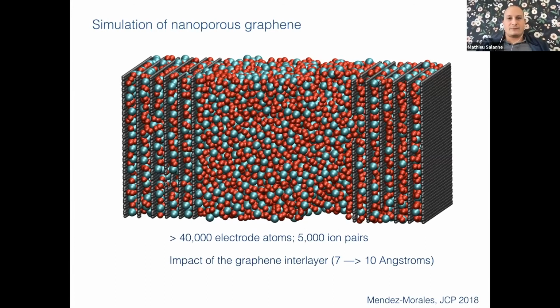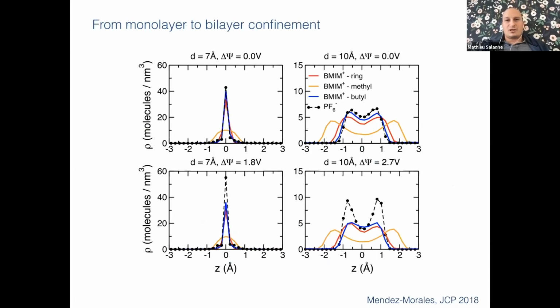So the idea is again to understand in particular the effect of the confinement. And so what we observe is that when you change from 7 angstrom to 10 angstrom, you have a very large structural difference, because in one case, you can only accommodate one layer of ions in the middle of the pore. While when you have 10 angstrom, you start to have more space, of course. So it's not really a bilayer, because in fact ions are in a checkerboard, so they will not be in front of each other. They will alternate like this, but in the end they are spread in a kind of bilayer inside the pore. And when we apply voltage, this does not really change. We enrich in cations or anions, but we keep this monolayer to bilayer.